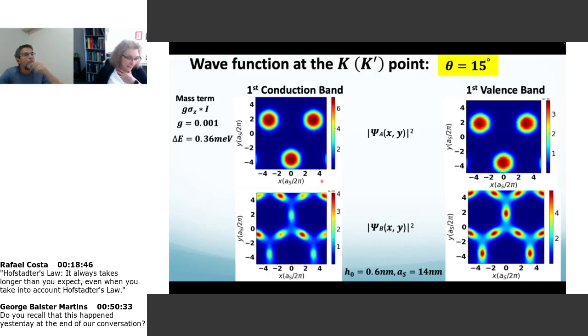When I look at the valence band, at the solution that has negative energy, the amplitudes in sides A are the ones that are 10 to the minus 26, tiny. So the whole wave function practically doesn't have any amplitude here. All the amplitude is concentrated in this region. This is the region that gives me Chern number different from 0. This is the region that gives me Chern number equal to 0. So this already tells me that the Chern number must have to do with these extended wave functions coming from the K point.